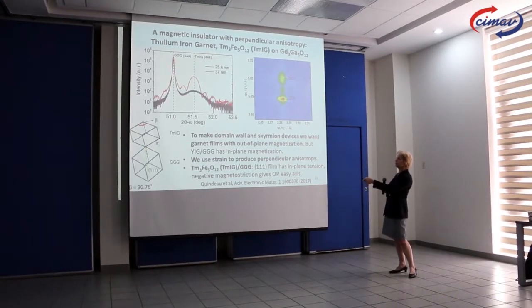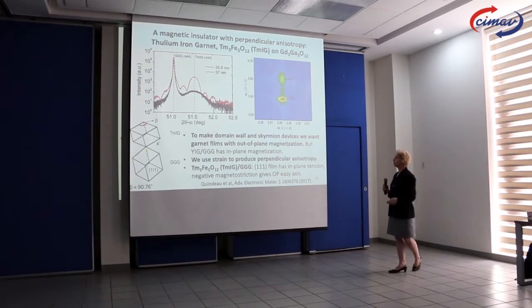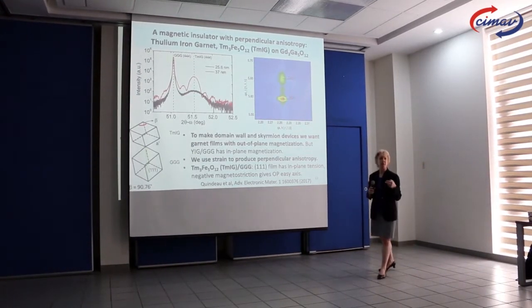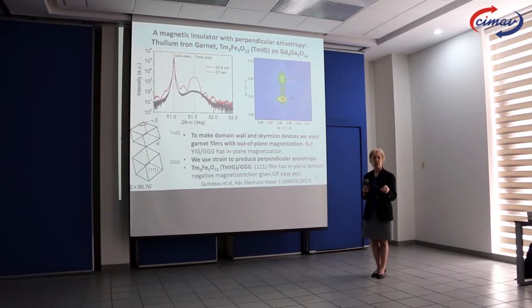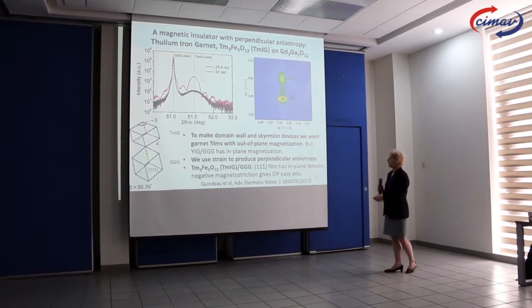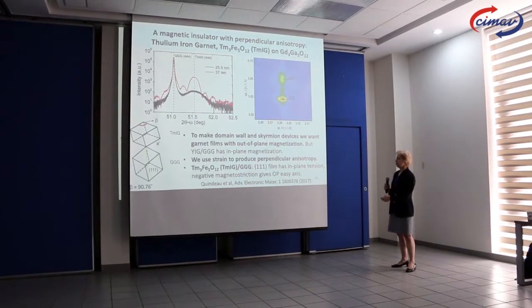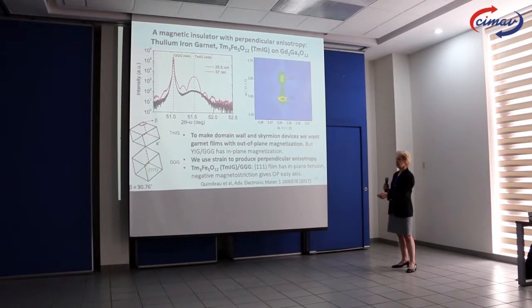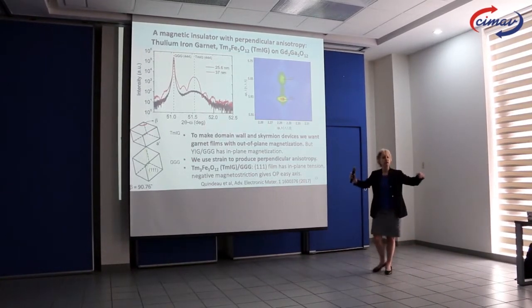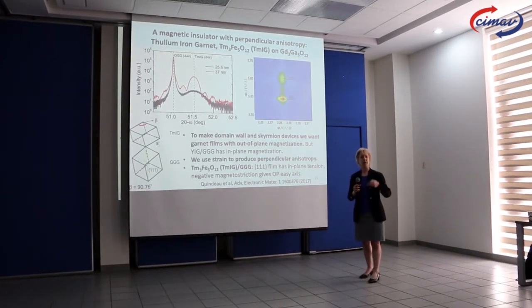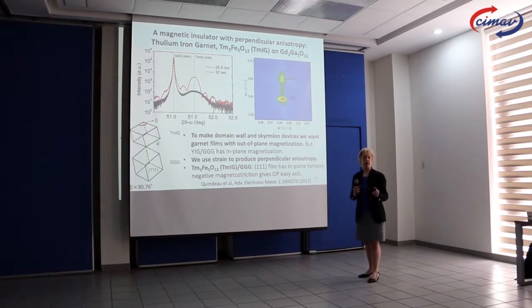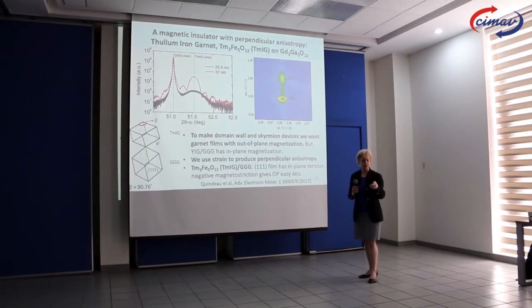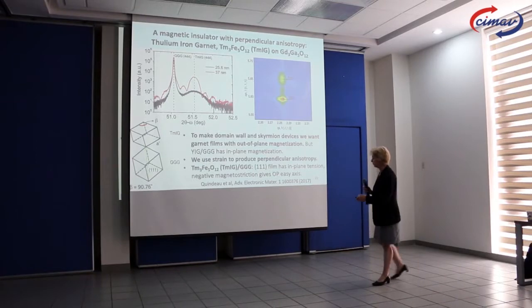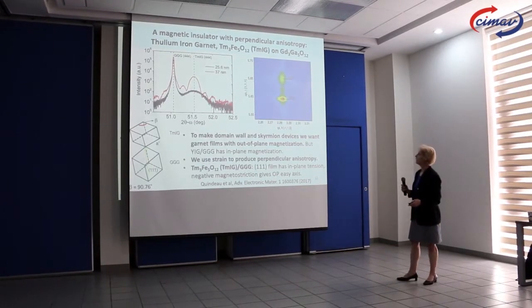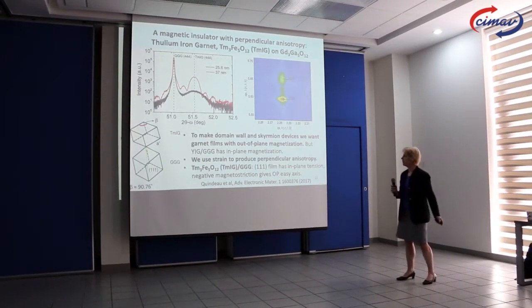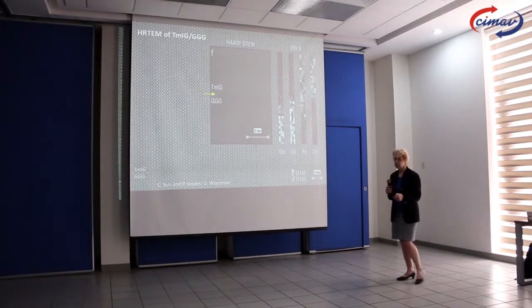So you can see some X-ray data here. This is a reciprocal space map. It shows that the material is epitaxial on the substrate, and because of the strain state, the thulium garnet is actually in tension, in plane. And because of its magnetostriction, that gives it an out-of-plane preferred magnetization direction. So we have PMA, perpendicular anisotropy, for thulium garnet on GGG.